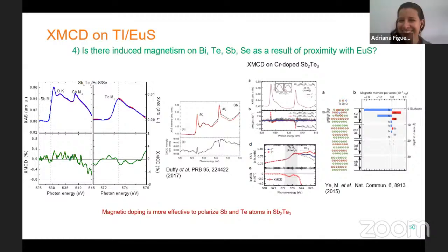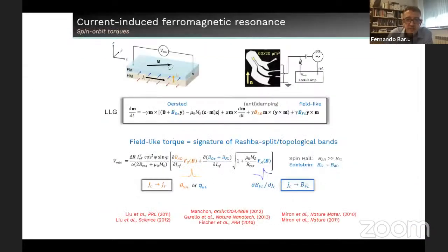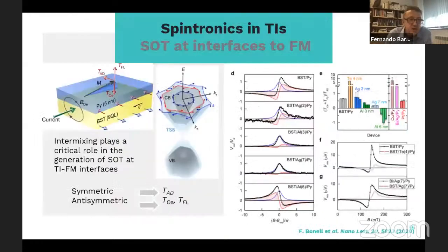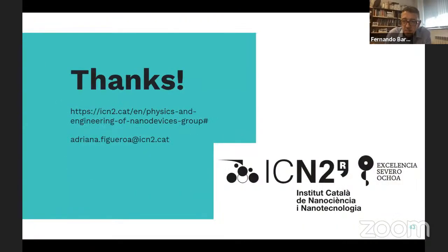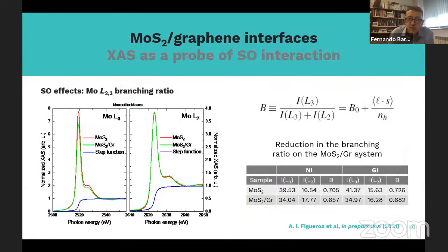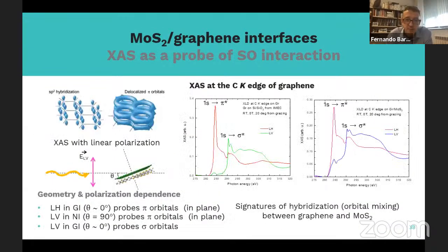Of course. Yeah, I have been really amazed by this carbon K-edge spectra you have shown. This changes really dramatically from a pure graphene, to what you expect from a two-dimensional sample, to something that looks much more like a diamond spectrum. So it goes really to sigma, yeah, to the complete opposite way.